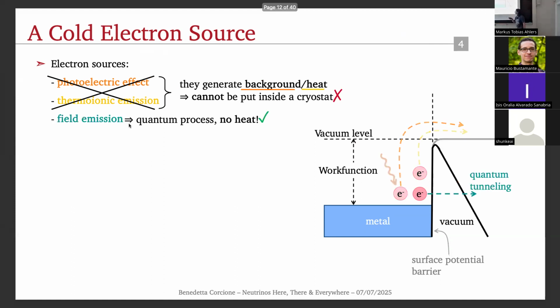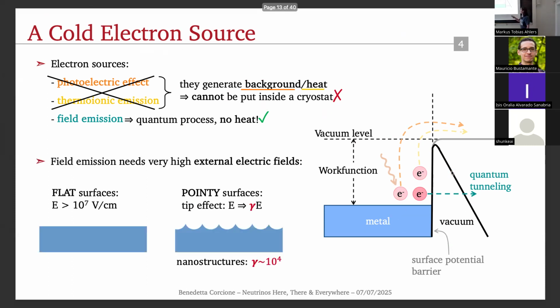So our solution is to use field emission. Field emission is a quantum process, so it does not need nor produce any heat. And in field emission, by applying a high enough external electric field to a metal, we can extract some of its electrons by which quantum tunnel the surface potential barrier. So it is good to be used in a cold environment. But we have to say that to generate field emission, extremely high electric fields have to be applied.